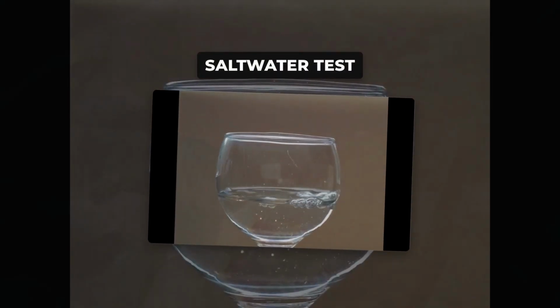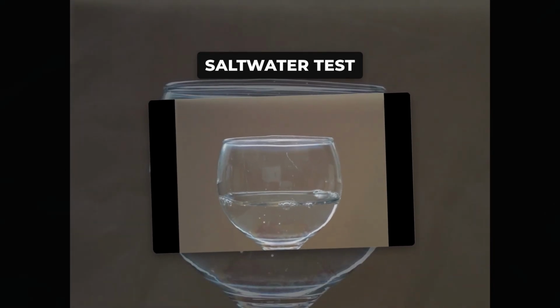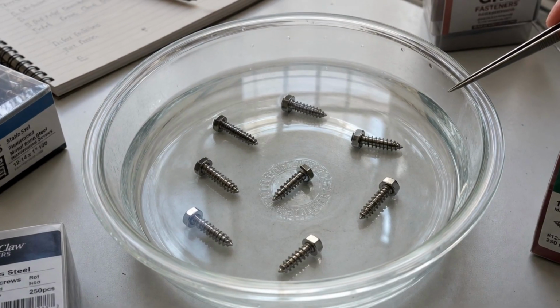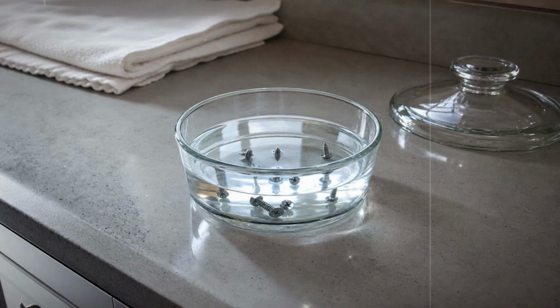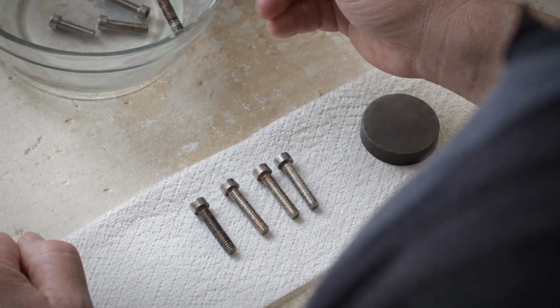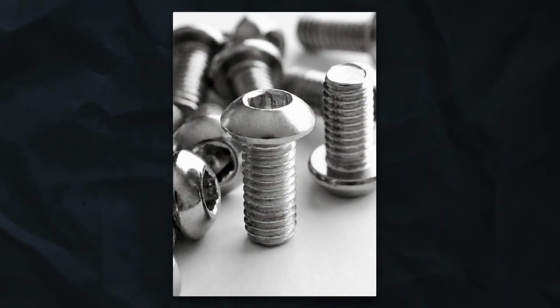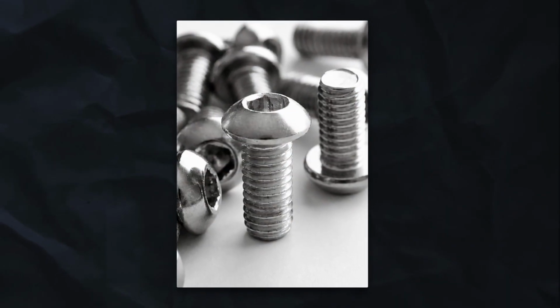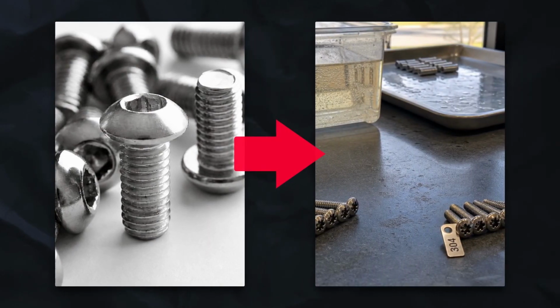Fill a bowl with water and stir in salt until no more will dissolve. Drop in 1 screw from each box you are considering, keep them from touching one another, and set the bowl somewhere out of the way for a day or 2. Then look at what came out. Genuine 304 and 316 emerge looking exactly as they went in.